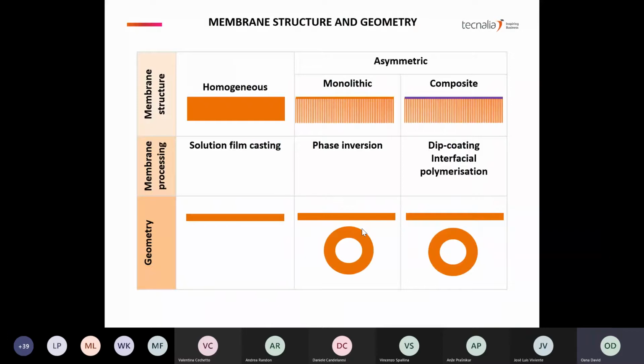So if we look at the membrane structure and geometry, here is an overall classification. A membrane can be also a homogeneous dense film that is made by solution film casting, but this kind of membrane is not found in practical applications. It is used to determine the intrinsic properties of a given material or polymer. All commercial membranes are asymmetric, and this is because the flux through a membrane is inversely proportional to the membrane thickness. And then the membrane itself is the top layer, which is as thin as possible. And because it cannot be self-standing, it's supported on a porous sublayer.